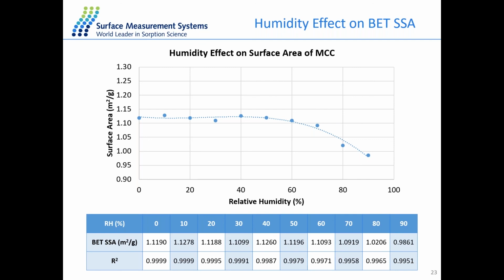So when the relative humidity in the environment is low, lower than 50 or 60%, the water content on the cellulose powder is also low, resulting in minor extent of granulation or caking. But under high humidity environment, the water content increases, resulting in a significant caking effect. And this could lead to the lower BET surface area that can be measured with the IGC technique. So this simple case study just demonstrates how the IGC technique could help to study the humidity effect on the surface area of this MCC sample.